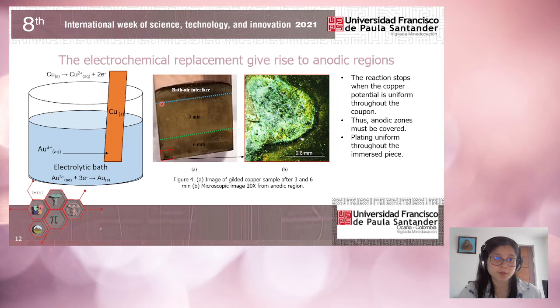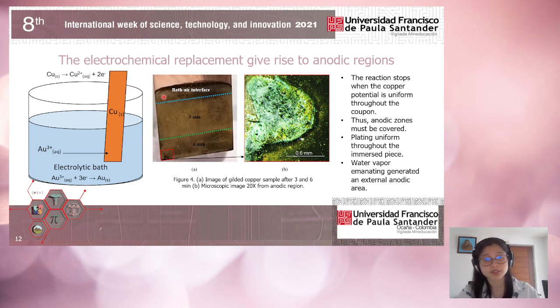Above the blue dotted line, you can see a bath-air interface. This was created when the water vapor from this electrolytic bath generated this oxide of the copper. It is important to notice that this anodic region suggests that the reaction could have gone even further than 6 minutes, since these anodic zones were still left uncovered.